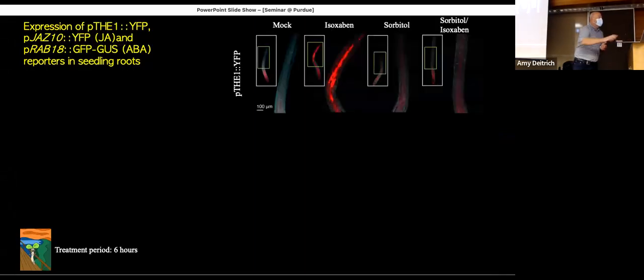So let's get started. What I'm showing you first is the expression of the promoter reporter construct for THE1 under the four different conditions in the root tip. As far as we can tell, THE1 seems to be induced by the isoxaben treatment in the area of interest, the late elongation zone. It's not really induced by sorbitol treatment. And interestingly, in the double-treated root, the expression is significantly reduced compared to isoxaben alone. So it seems to be responding the way we would expect.